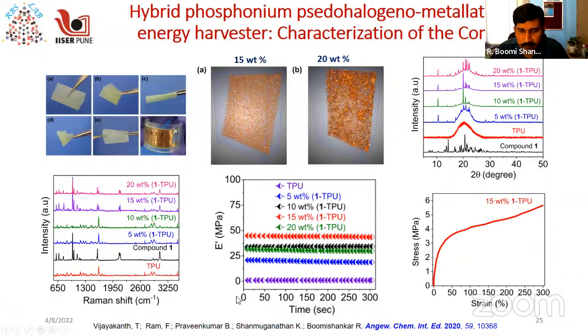As you stretch the material for different durations, there is no change in the strain in the system observed. However, they can also show a higher strain at higher loadings, which means that the material is more robust than the simple neat unloaded polymer itself. The best performing polymer can be stretched up to 300% strain, which means the material is very robust. The composite does not give up its elasticity even though you have crystalline particles loaded in your system.